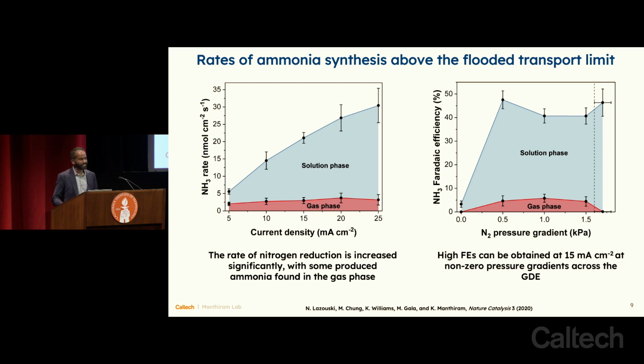The second benefit of this is not just that the rates are higher, it's that the Faradaic efficiencies are now also much larger. So what was just 8% before for this one-pot realization, just by solving this transport problem, by getting the nitrogen to where it needs to go in the reactor, we can now get nearly half the electrons to go to the right place. We have a Faradaic efficiency of nearly 50% now by implementing the gas diffusion electrode.